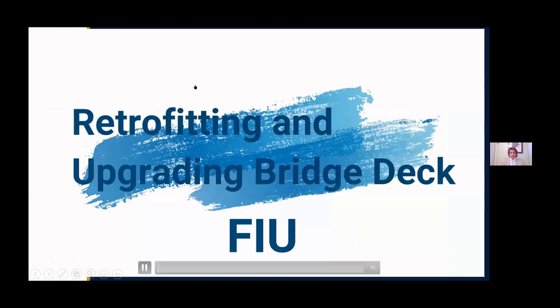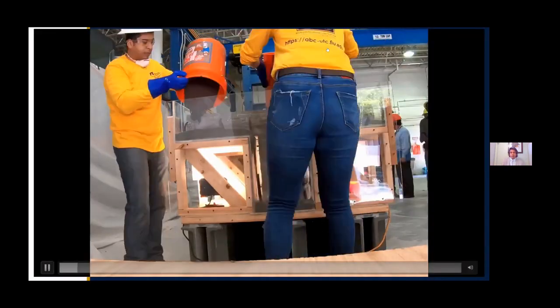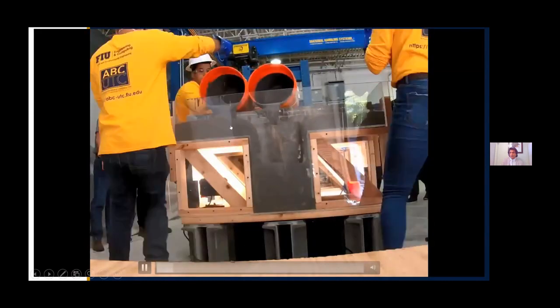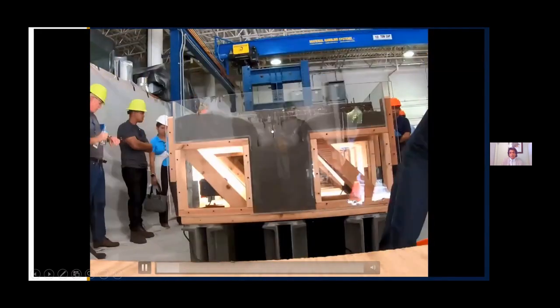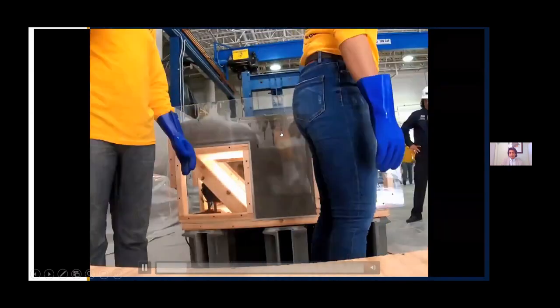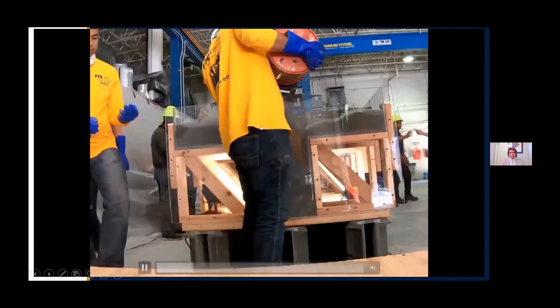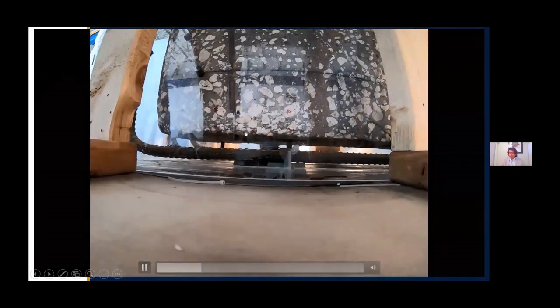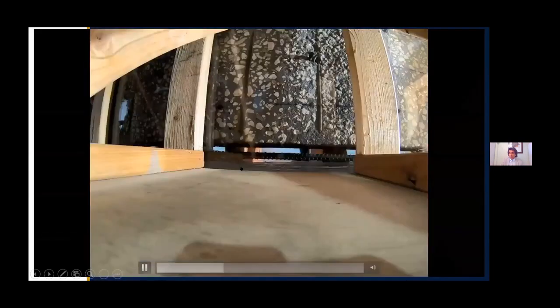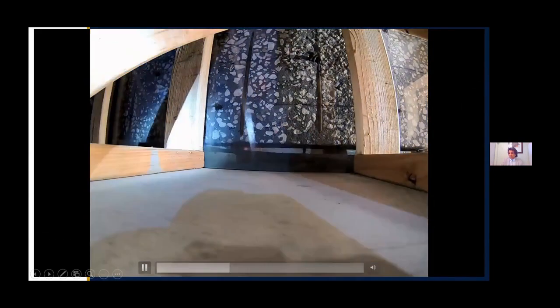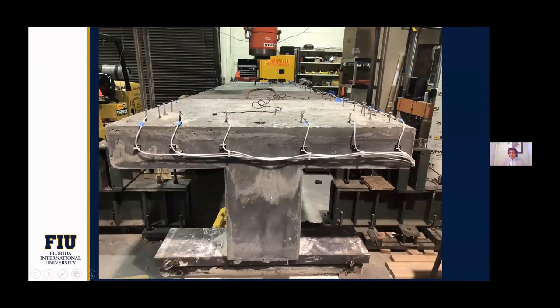And I'm not sure if you can see this video. So in fact, this took a long time because we had to mix the concrete and then dump it using a bucket. So even using this long process, we didn't have any honeycomb or anything like that. This UHPC flowed around the formworks, filled all the gaps, attached compositely with the existing deficient structures. And I can show you, this is the end product, very nice.